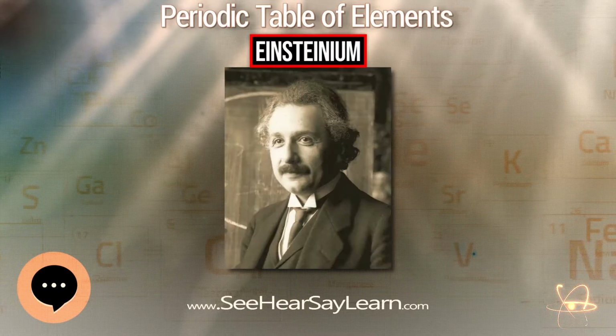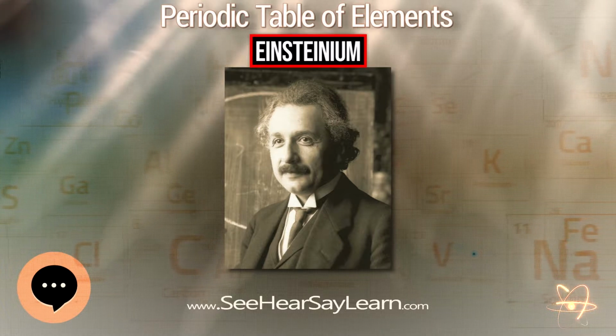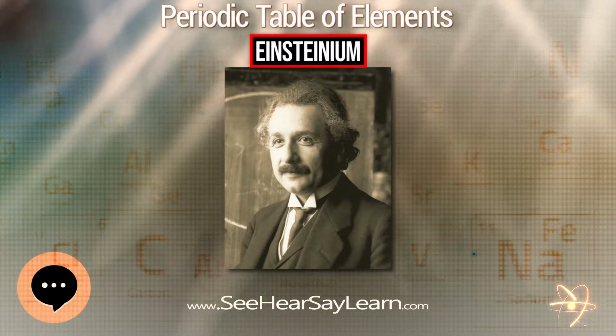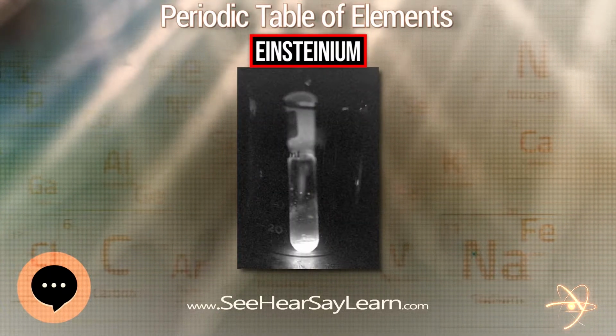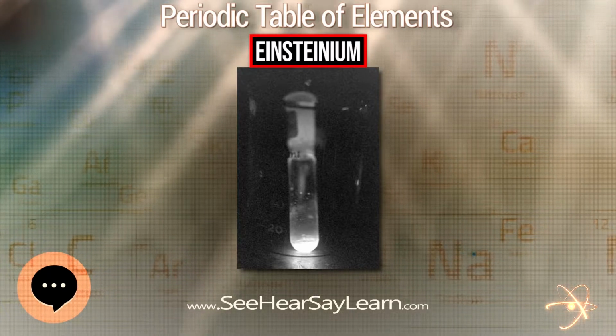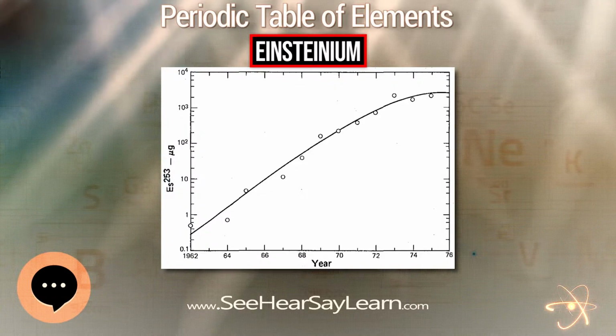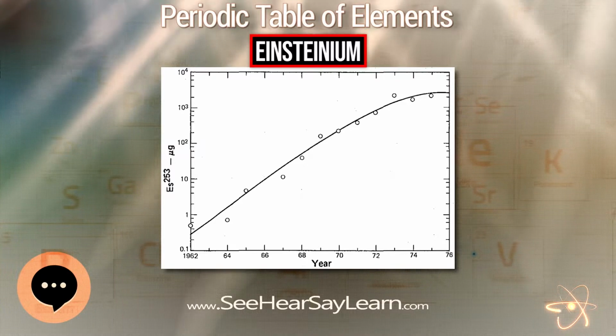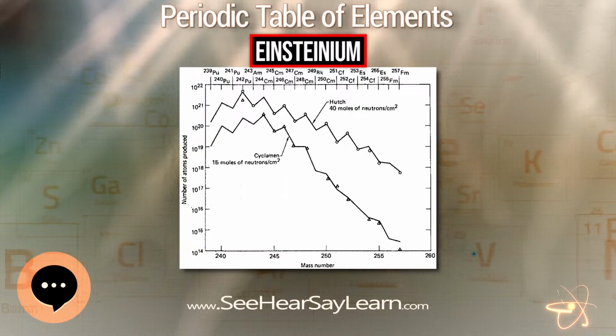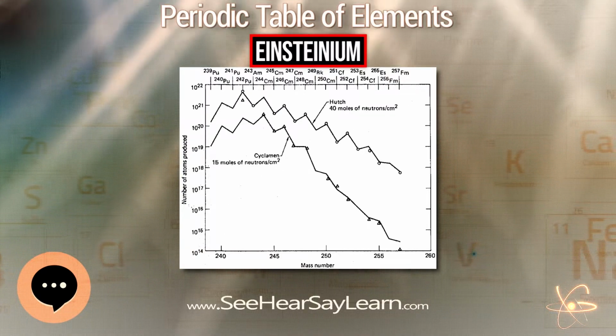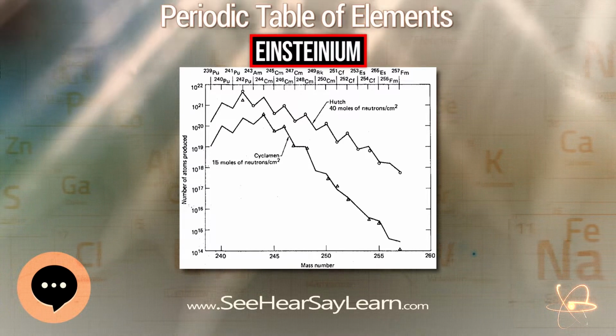In order to reduce the self-radiation damage, most measurements of solid einsteinium and its compounds are performed right after thermal annealing. Also, some compounds are studied under the atmosphere of the reductant gas, for example H2 and HCl for EsOCl, so that the sample is partly regrown during its decomposition.